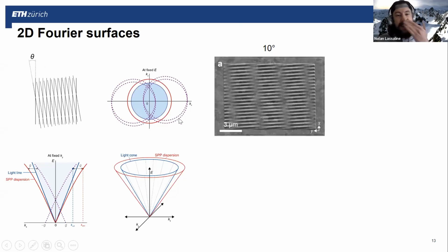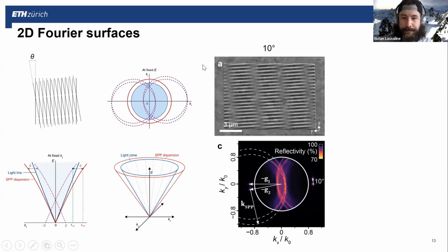The first interesting thing is that to some degree, this does look like a one-dimensional grating, but if you look closely, you see elements of intricacy and complexity that come from the fact that we're superimposing 2 sinusoidal functions. And what's very satisfying is that the data comes out exactly as one would expect from Fourier mathematics. This data reflects this cartoon here, and this is a reflection measurement. And so we nicely see our 2 pairs of circles that come from the 2 Fourier components.